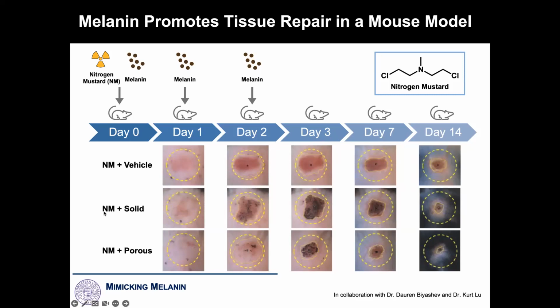So treatment and then the countermeasure, which is the therapeutic solid or porous melanin. And so we're now treating, right, at day 1, we're introducing the melanin particles. And after 14 days, I think you can see that we can measure this and we can see that the injury, actually, even at day 2, you can really see in this case, with the swelling has gone way down. We have statistics on the next slide. But what I really like about this is this demonstration that in this case, the fur has now grown back. And so it's obviously recovered faster.